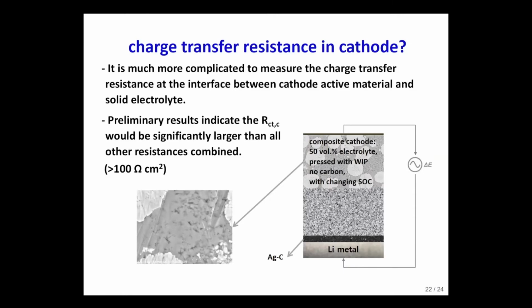The reason should be further explored, but it can be from insufficient physical contact at the interface, or it can be from chemical degradation at the interface. If we look at this cross-sectional image, the physical contact looks good, but it is too early to say that this is the true reason.